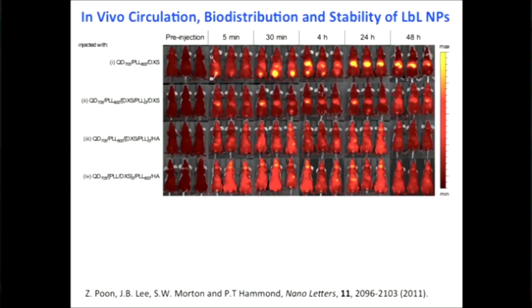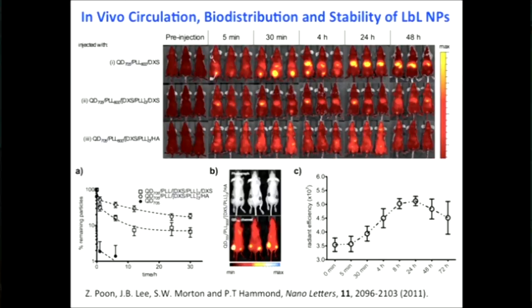Now, we introduce these negatively charged, highly hydrated hyaluronic acid on the outside and tail vein inject the mouse. And look, this nice, clean light up all over the bloodstream of the mouse that extends out for, you know, essentially what looks like a couple of days. Actually, the half-life is more like about 18 hours. And here you can see some of that half-life data, looking at the quantum dot getting ejected very rapidly, the dextran sulfate hangs around but not very long, and the hyaluronic acid hanging around for much longer.